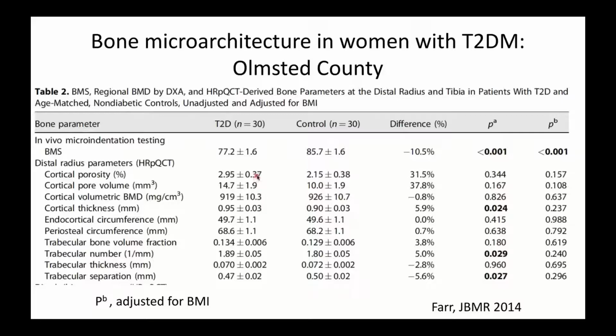Porosity, by the Scanco, there is a little trend that you see to be higher in diabetics, but it's not significant, also pertaining perhaps to relatively low number of patients. So that first study did not confirm the concept of cortical bone porosity in diabetes, and rather showed a trabecular structure and cortical structure, if anything, slightly better among diabetics than not.